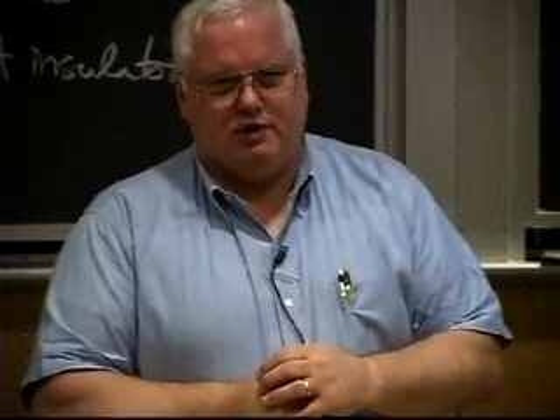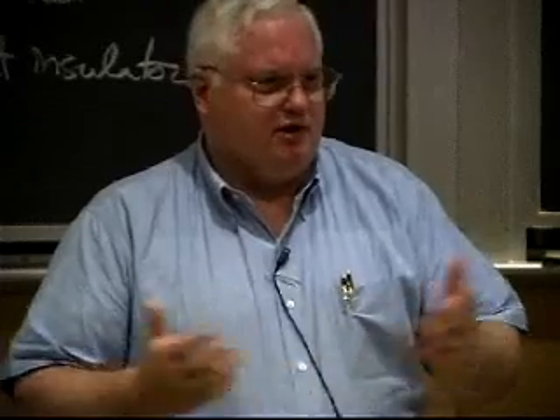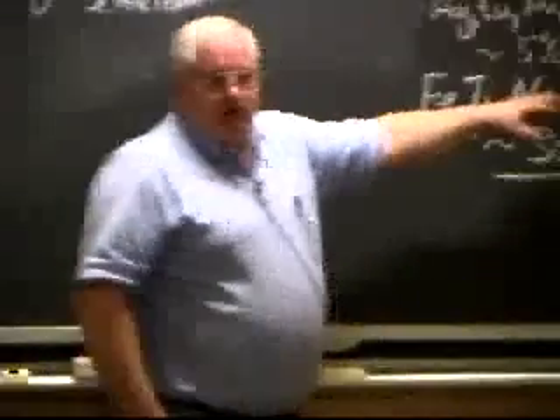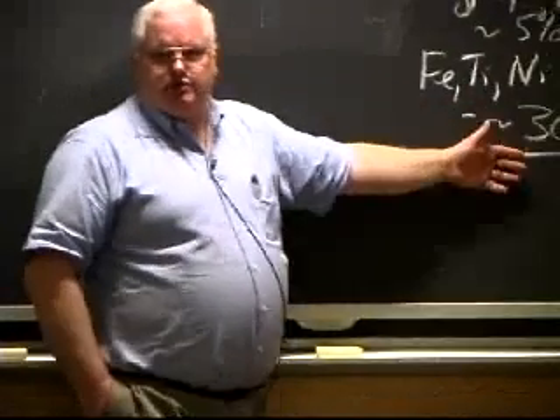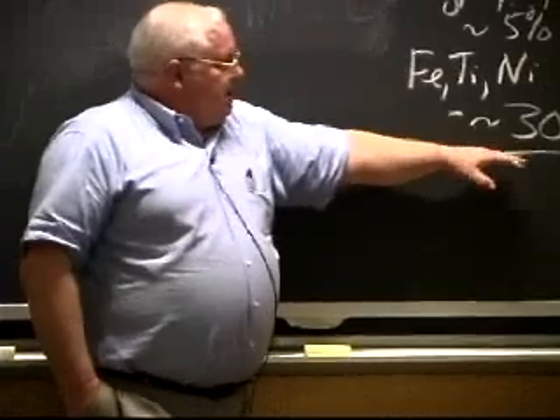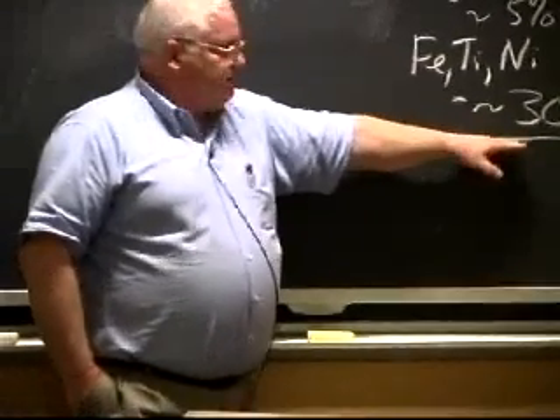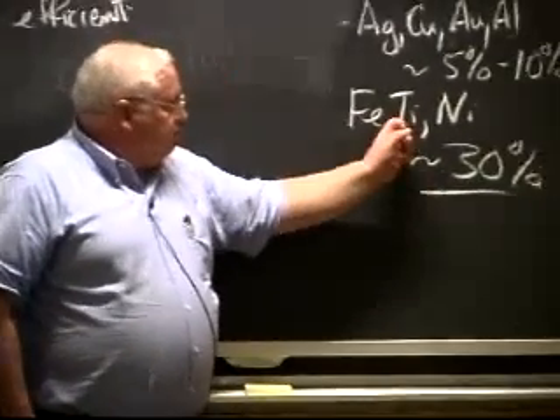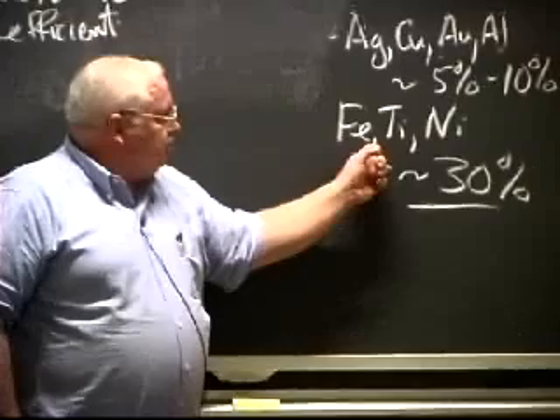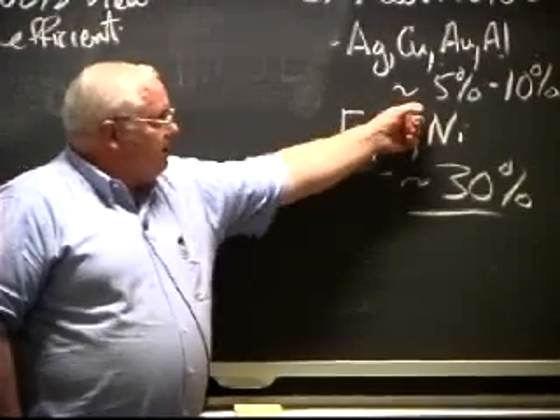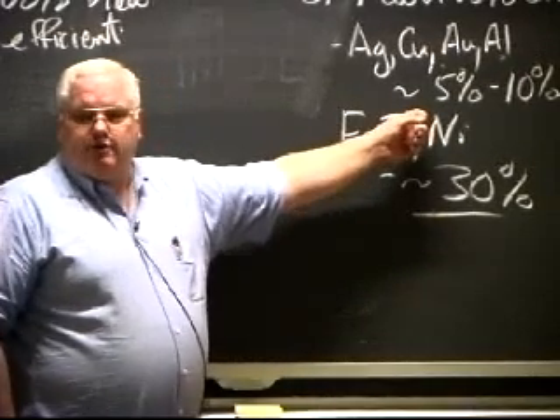We make aluminum instruments. I said, you do? Because I would have thought aluminum instruments would corrode and stuff. He says, no. So we went and did studies of aluminum and titanium and other things, because they use titanium instruments and stainless steel. And sure enough, you can measure 30% absorption on your nickel and your iron and your titanium, your stainless steel, and you measure about 5% absorption on the aluminum.